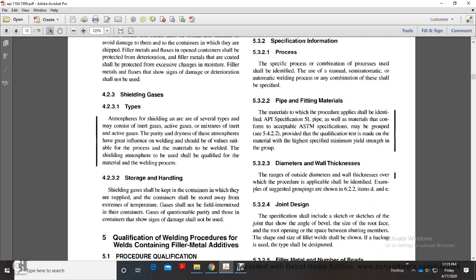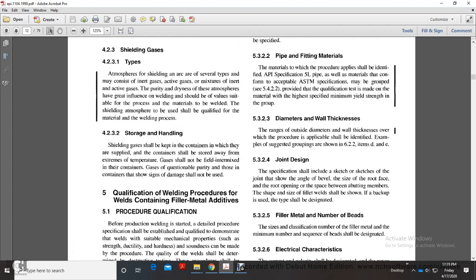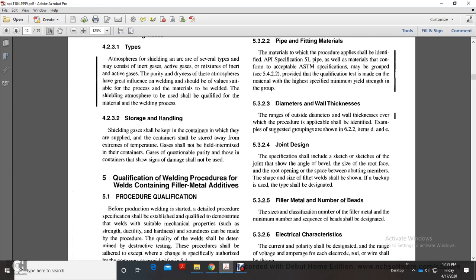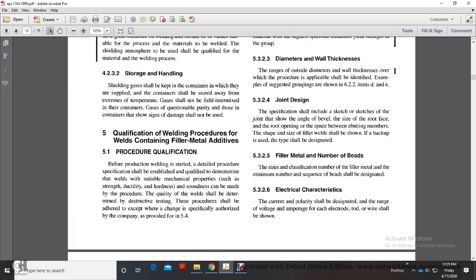5.3.2.3 Diameter and wall thickness. The range of outside diameters and wall thicknesses over which the procedure is applicable shall be identified, with examples of suggested groupings shown in 6.2.2, items D and E. 5.3.2.4 Joint design. The specification shall include a sketch of the joint showing the angle of bevel, the size of the root face, and the root opening, the space between the abutting members, and the shape and size of the fillet weld as shown. If a backup is used, the type of it shall be designated.